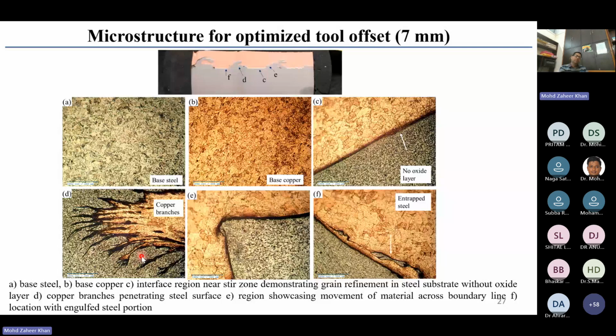Second important thing that you will be noticing over here is that your base material is having certain grain size, as you can see from the micrograph, but after the cladding has been carried out and stirring of the material has taken place, the substrate material has also become very fine. So there is no grain coarsening that has occurred in any of these situations.